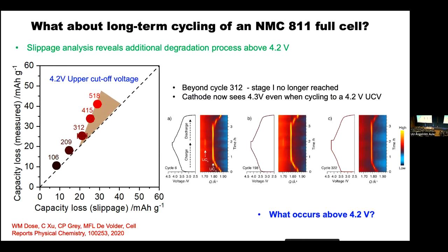And what he showed was in a full cell, if you just continue to cycle with a 4.2 volt upper cutoff, the degradation tracks a linear relationship between the loss of capacity and the slippage until you get to about 312. Then suddenly the slippage starts to increase, indicating that there's another degradation process on the cathode. Now, there's nothing particularly magical about 312 cycles. What's going on is that at that point you have so much slippage that the anode can no longer be fully lithiated. Instead of lithiating all the way down to stage one graphite, the fully lithiated graphite, you only get to stage two.